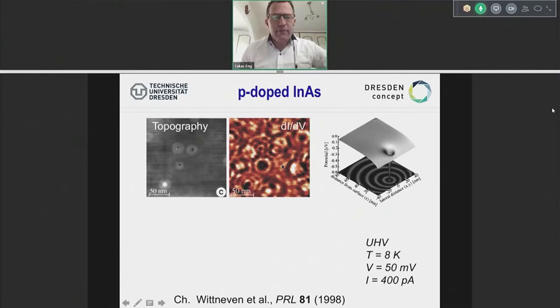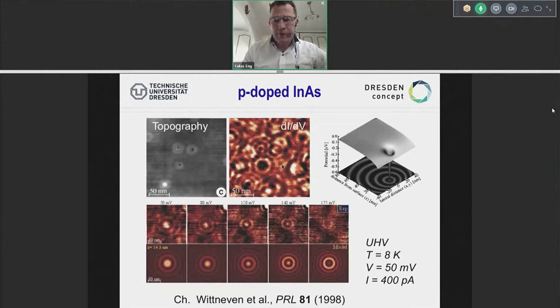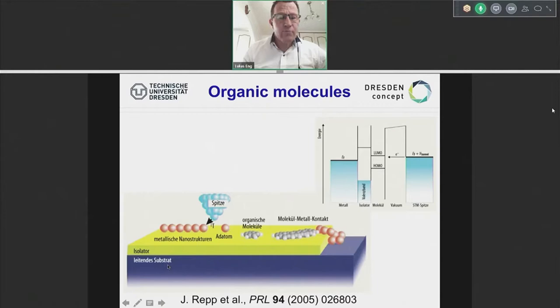So they said, okay, let's plug in our computer and look a little bit more at what's going on by changing the bias voltage V of my tunneling microscope from 50 millivolts, as shown here, to different regimes: 50, 80, 110, 140, 170. So they took one defect, like shown here, made an analogous simulation, which is exactly this kind of earthquake simulation and exactly the cut that you see at the sample surface. And if you now compare the theory with the experiment, you see that this is really overwhelming, fitting very well.